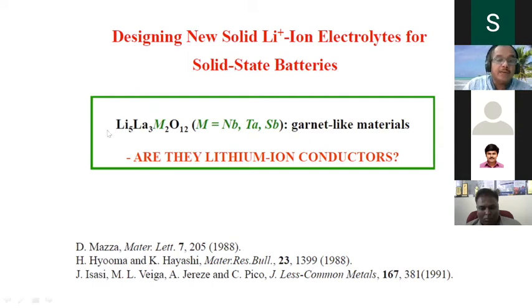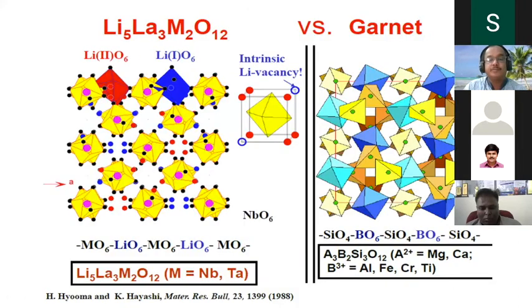Why our group is much interested is these compositions. Li5La3, the best composition for us is the titanium. But titanium is the biggest problem. But this system is interesting. Instead of titanium, we are having niobium, tantalum, and antimony. So, which means that we can think about these materials as fast lithium ion conductors. If these materials are fast lithium ion conductors, then we can think about electrochemical stability. That's how the research started in 2004 or 5.